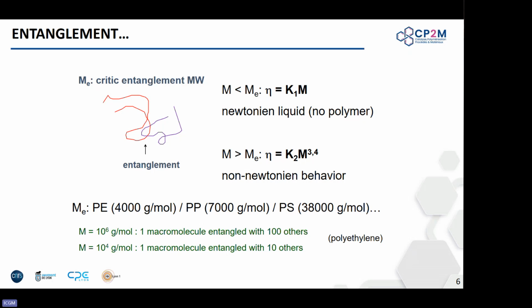So just a comment, if you have a molar mass for polyethylene of 10,000 grams per mole, you have one macromolecule entangled with 10 others. So it's just to give you a rough idea. And if you have 1,000,000 grams per mole, then one macromolecule is entangled with roughly 100 others. And that explains why you have such different properties in the melt, for instance, or on the final product.